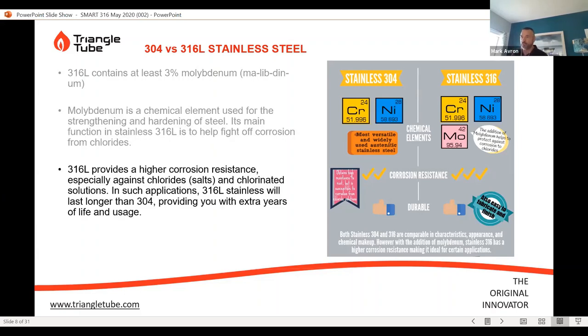against chlorides in water. So when we start talking about water, you've got chlorides that exist. These are salts in solution, and they either happen naturally through the ground, depending upon the region that you're in, or in areas where we have high snowfall and they're using salts to melt snow, or sea coast areas, those salts make their way into the groundwater. And they're very corrosive. So the 316L adds to that corrosive resistance. Right? And then in some areas, chlorine is actually added to water supplies.